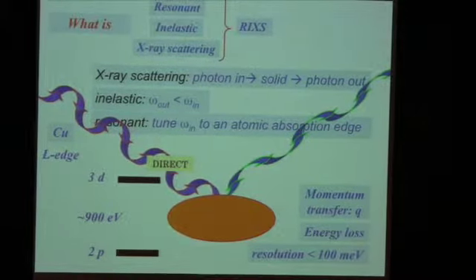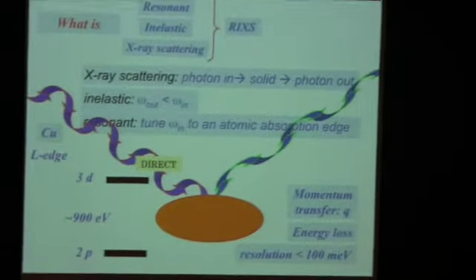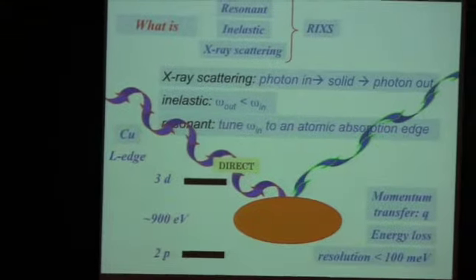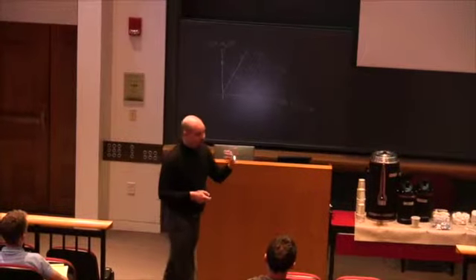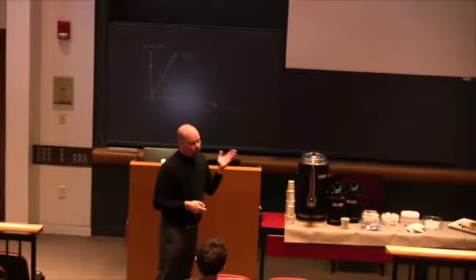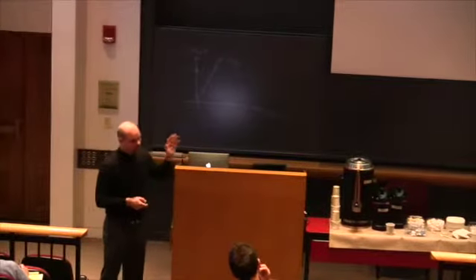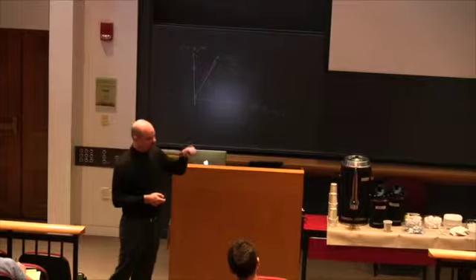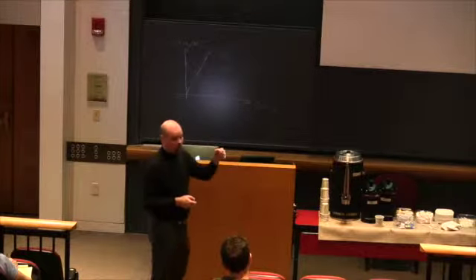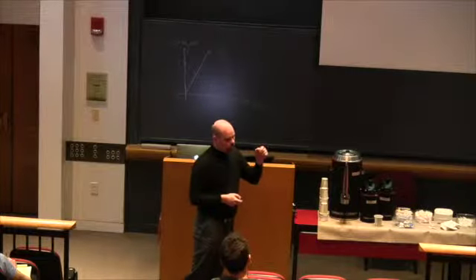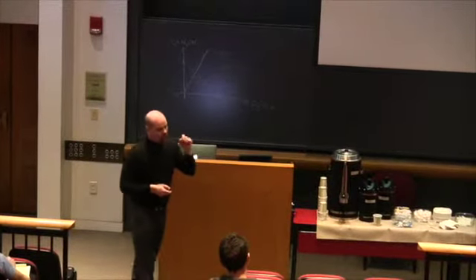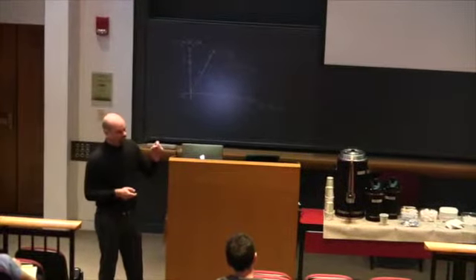So the first RIXS experiments I will show you were done with 100 meV resolution at the Swiss Light Source. RIXS was a rather obscure technique, it was one beamline. The Swiss had a very good sense of their science case, and they did this where nobody was really doing RIXS. After some of this stuff I'll show you, and especially after we showed theoretically and they found experimentally that you can do spin flip RIXS, there have been, I think, now 6 beamlines. So there are 4 still being built to do RIXS.